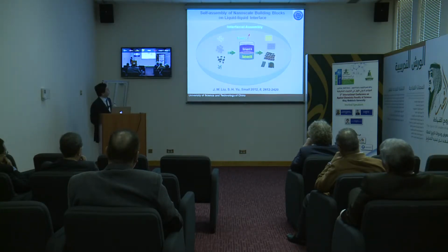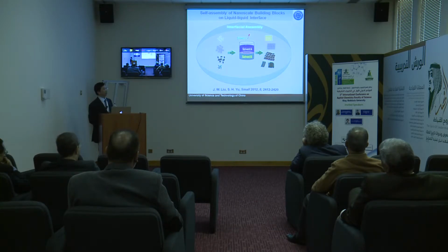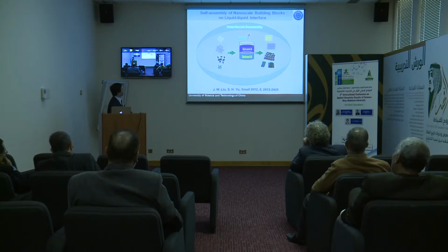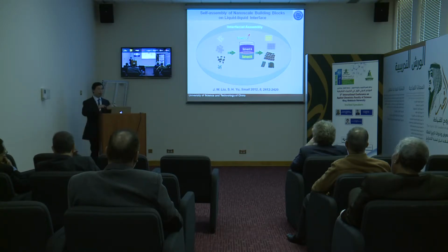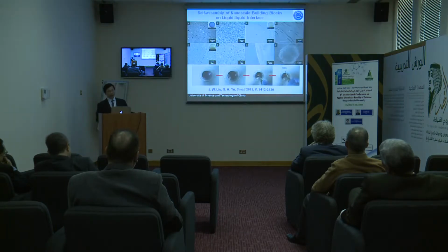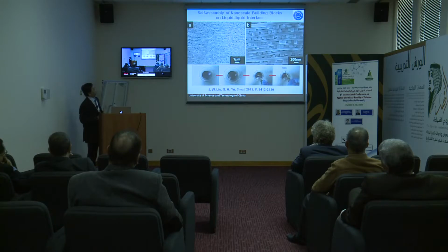application. And then later on we introduce solvent A and solvent B, which are insoluble with each other. But the interface will be here. Then you can introduce this interfacial assembly strategy. You can make different kinds of nanostructures become thin films, and you can even co-assemble nanocrystals with our nanowires. You can make different nanowire hybrid systems. So this indicates this interfacial assembly strategy is quite general for you to self-assemble different nanoscale building blocks in the future.